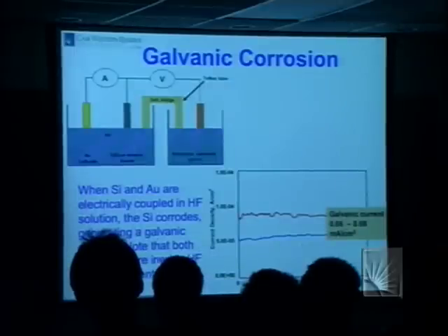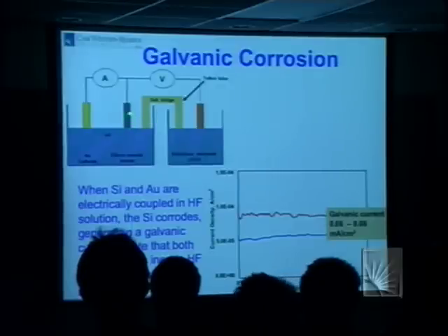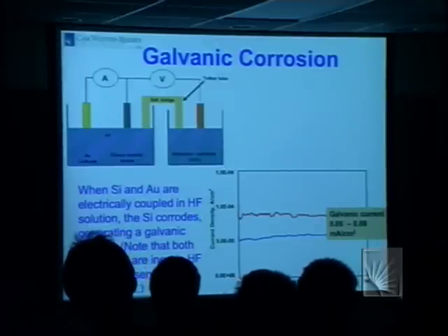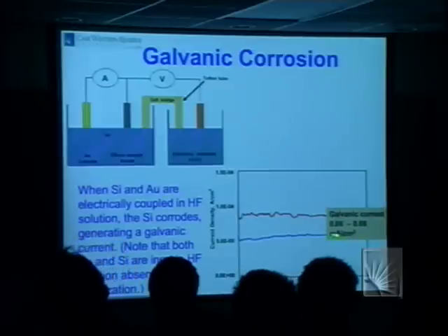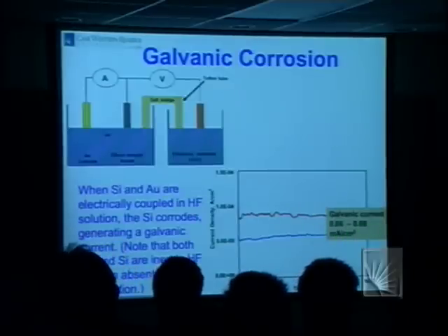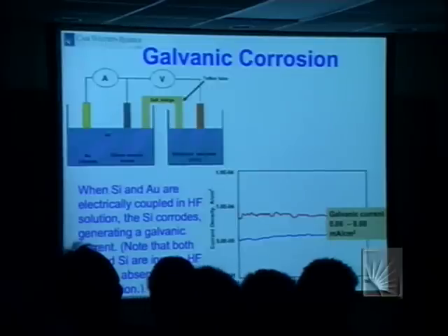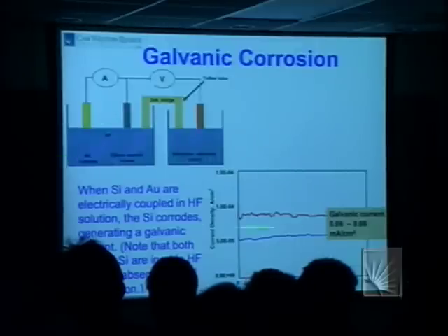So Joe Pear and I and Hal Kahn, a graduate student, set up this experiment. This is a typical electrochemical experiment. There is HF solution, a gold cathode, a conducting, doped silicon anode, and just a salt bridge to a reference electrode. And lo and behold, there is some significant current flowing, a galvanic corrosion of this magnitude. Although silicon itself is immune to corrosion in HF, and gold itself is immune in HF, when you make an electrochemical couple, you get some current flow.